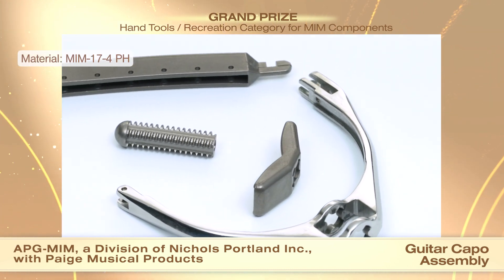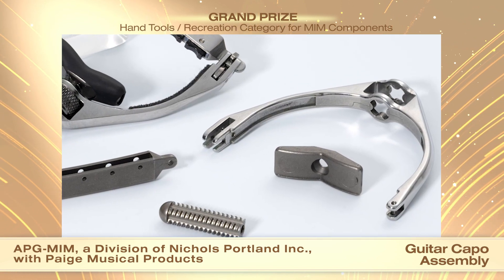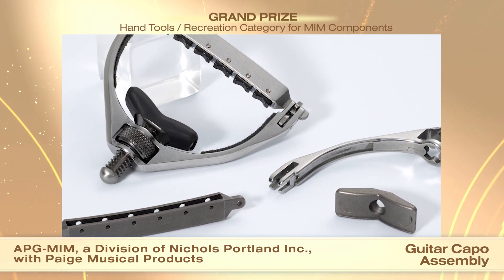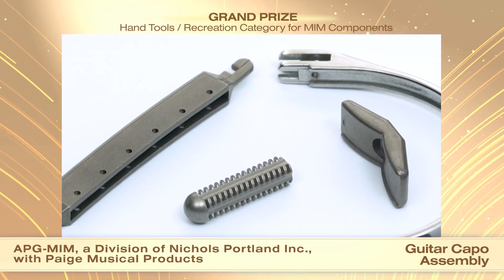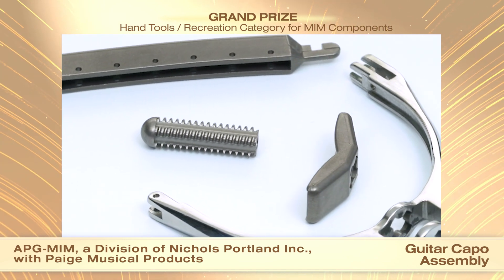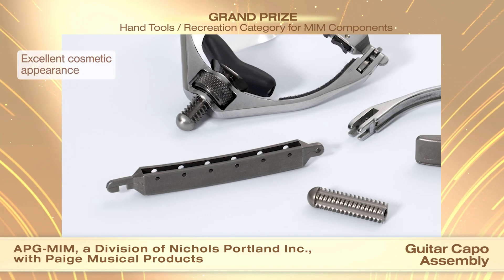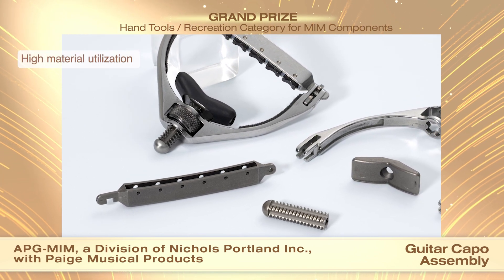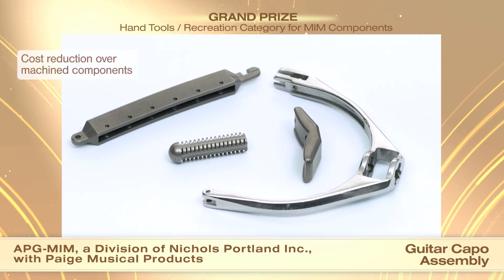Each of the three parts is made using MIM 17-4PH stainless steel. The challenging part design led to issues with tool design, molding, debinding, and sintering operations. All hole diameters are held to less than 0.04 millimeters total tolerance as sintered, with no further processing required. The yoke profile is held tightly for the overall size of the component to assemble properly with the bar. The star-shaped profile on the yoke needs to match the threaded design of the adjustment guide. The saddle and bar are highly cosmetic components that require precision-polished tooling. With all critical components manufactured at one source, there was greater part design flexibility, ability to iterate changes within the assembly, and cost reductions over machined components.